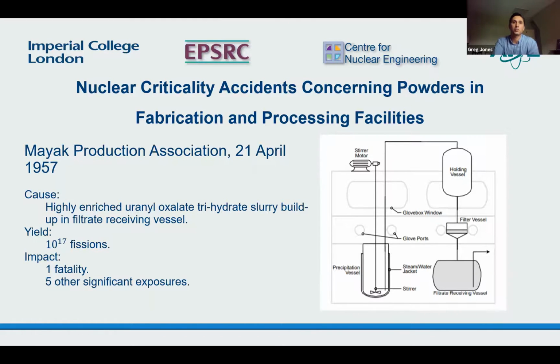During vacuum filtration, where it would go up to the holding vessel, through the filter vessel into the filtrate receiving vessel, a batch of uranyl oxalate trihydrate slurry was observed going into the filter vessel, and then as it dropped down, there was a violent release of gas and the ejection of precipitate onto the glove box floor. Ill-advisedly, the operator picked up the slurry with his hands and put it back into the filter vessel, and he felt ill quite quickly. Gas and vapor were released for a further 10 minutes or so until enough of the solution had been ejected that the transient stopped.